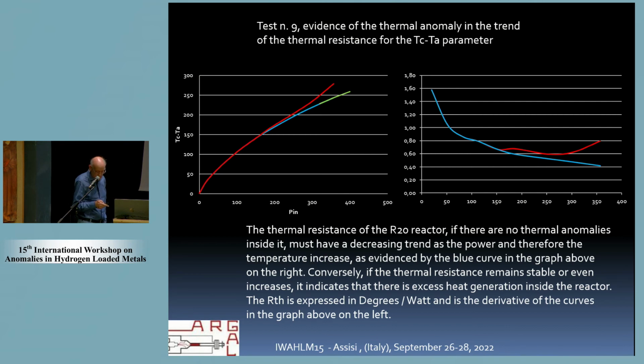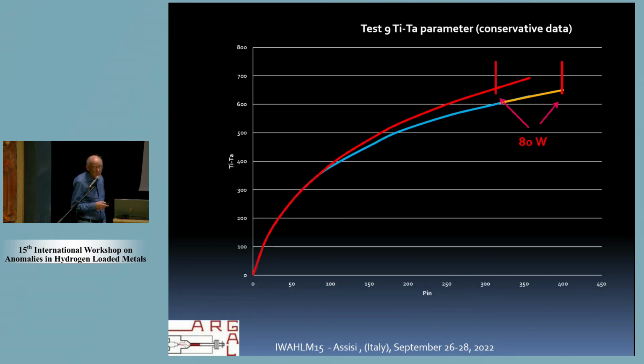Here there is an evaluation of the extra power produced in a conservative way. We compared the calibration temperature and the experiment temperature with hydrogen, and you can see that this distance represents the power — about 80 watts. If you could measure this difference from here to the extrapolation of the calibration, it should be much more.